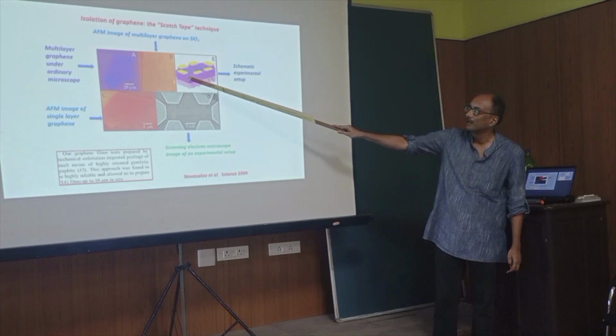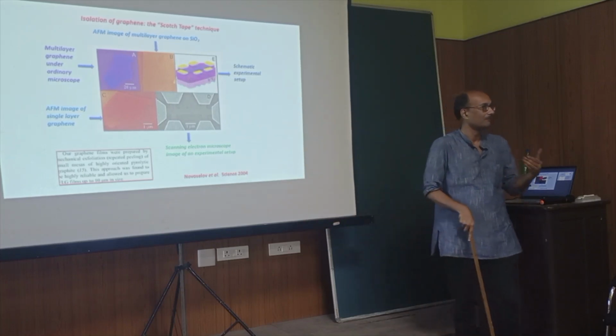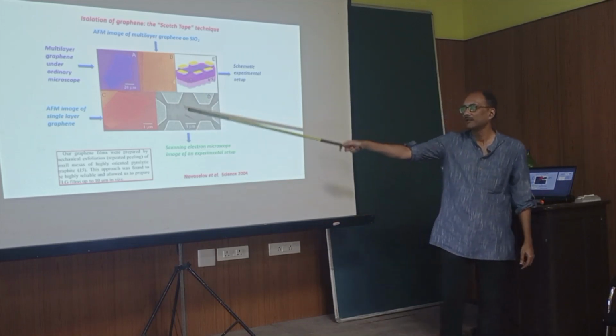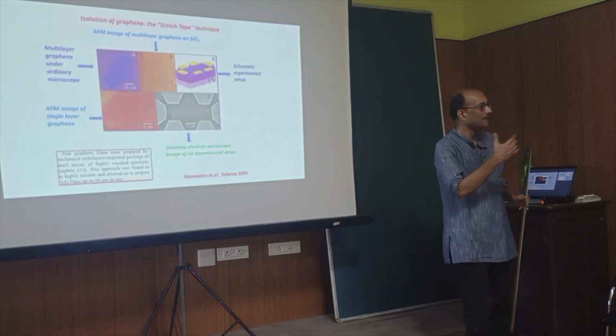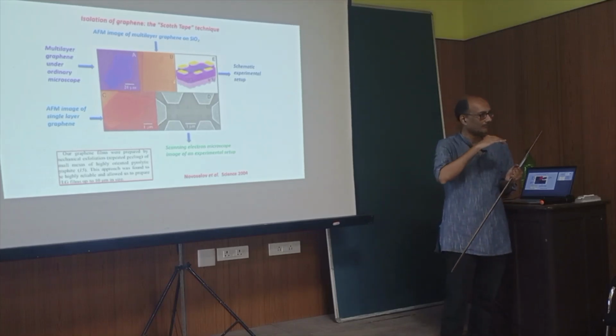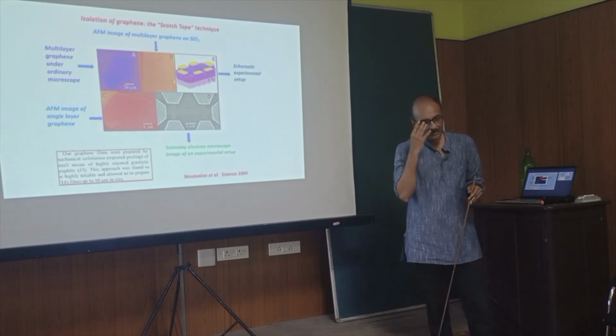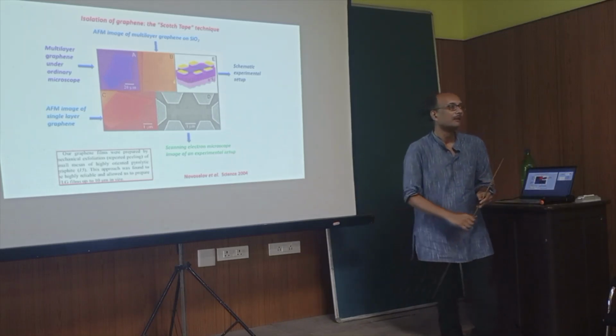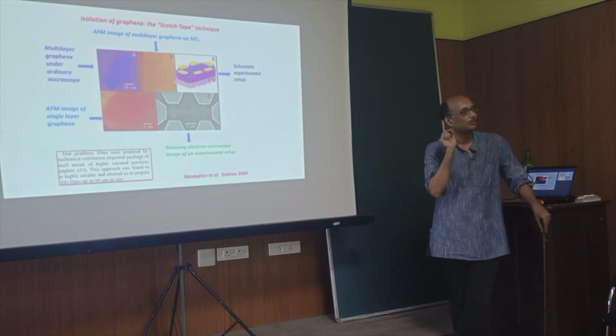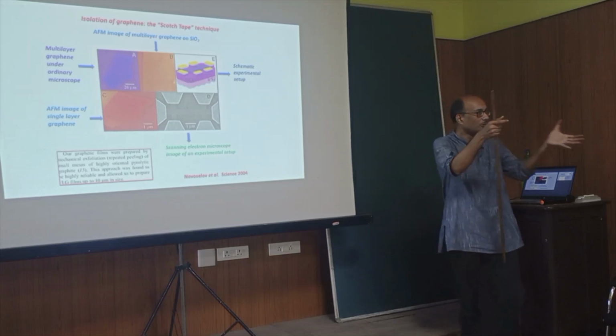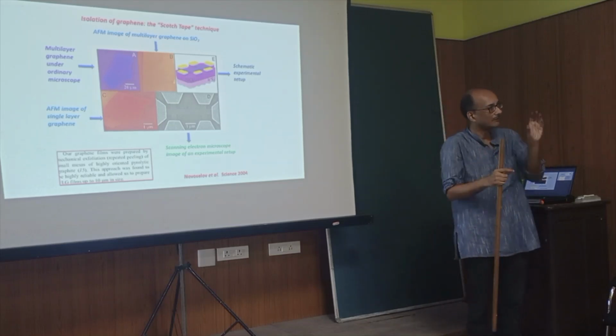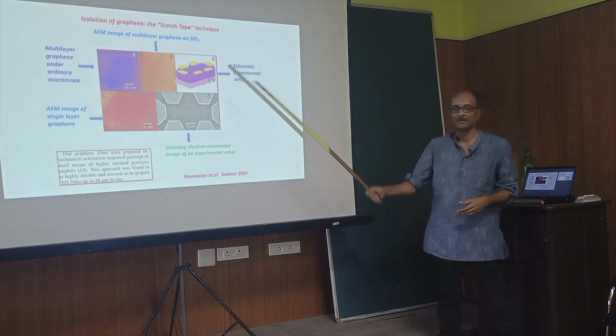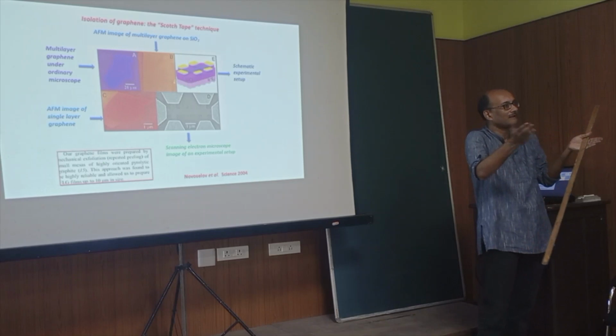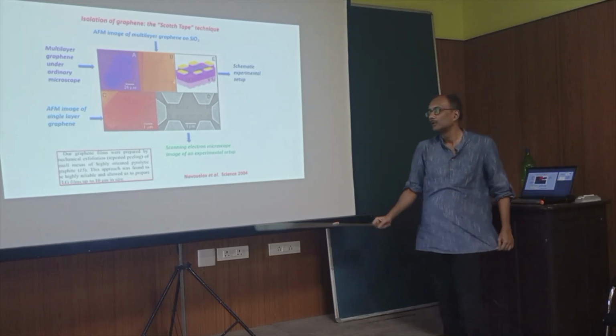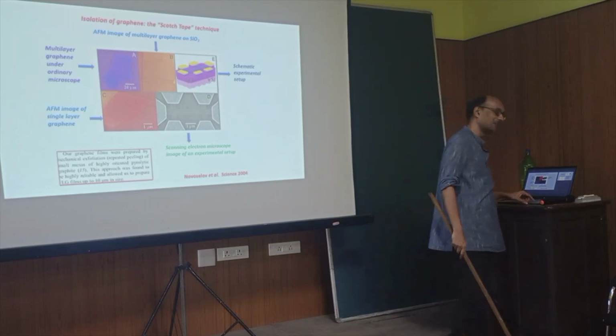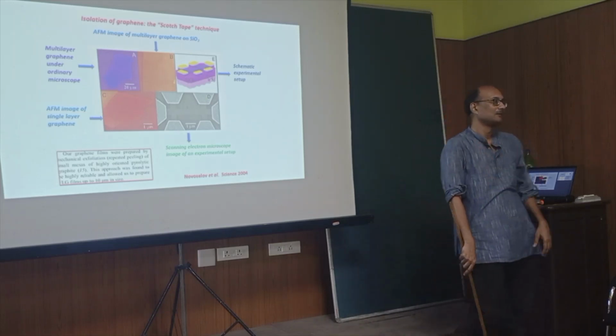After that, all he did was take this piece, the first known graphene, and put some electrodes around it so that they could make measurements on it. This was the first science paper showing that this two-dimensional structure of graphene could indeed be realized. It also solved a long-standing debate, because it was argued that a freestanding two-dimensional structure cannot exist: if you try, it will simply roll under its own weight and form a curly structure. But this didn't happen, and one of the reasons was the scotch tape, which provided the surface on which you could lay it. So this was really revolutionary for materials, the first known two-dimensional material.